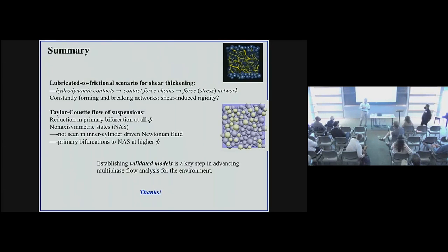The source of this, you can do it based on charge in an aqueous environment and getting counter ions. In many cases, like in cement, what people will do to get this behavior is throw in some comb polymers. They're polymers that have a backbone with little chains off the side, and they'll lay down on the surface and create a brush that has a very strong osmotic pressure to push those chains together. So those are two ways of getting that type of behavior.